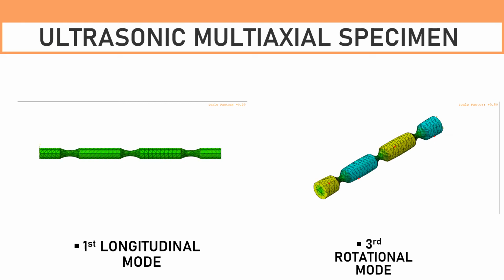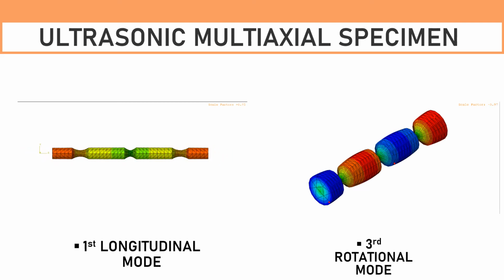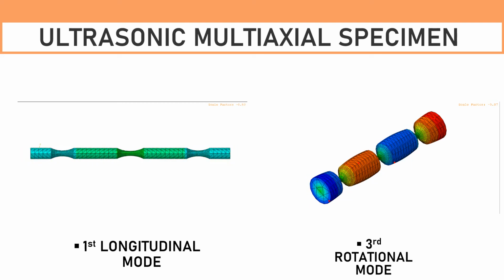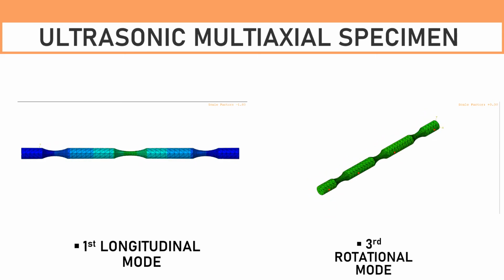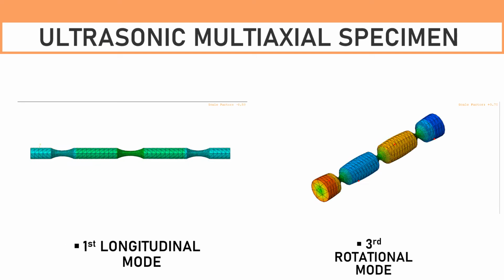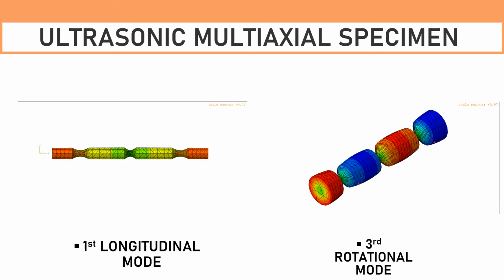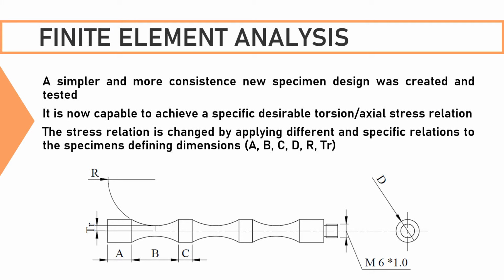Here we can see both movements of each mode, the first longitudinal mode on the left and the third rotational on the right. When excited, they are in phase, and the highest point of stress is simultaneously achieved in the middle throat. Throughout our work, we have changed the geometry of the specimen, maintaining always the three-throat specimen. The final geometry we are using in this work is much simpler and much easier to machine, giving more consistent results. It's defined by 6 dimensions, and by altering the dimensions in a specific way, we can achieve a different shear axial stress state.